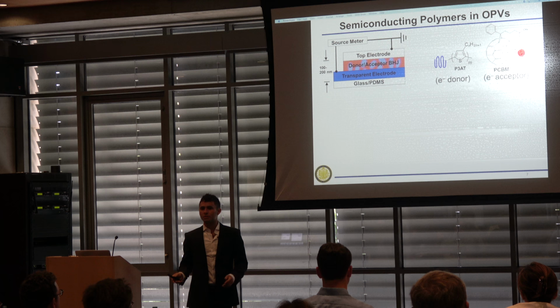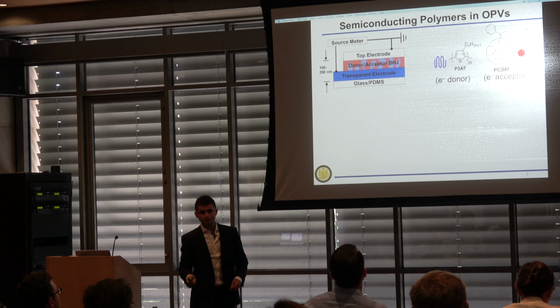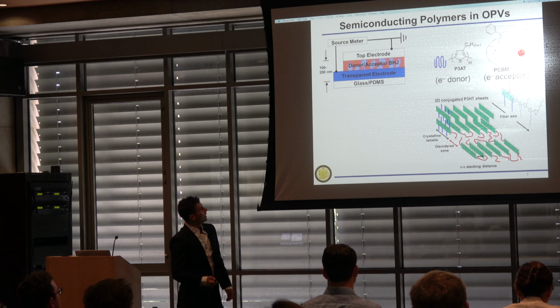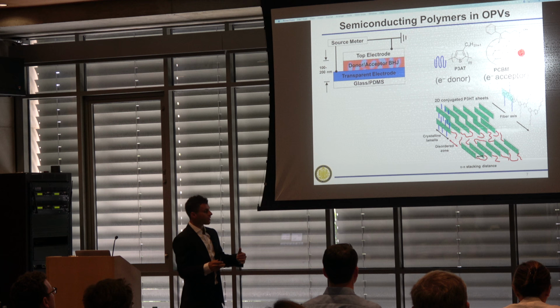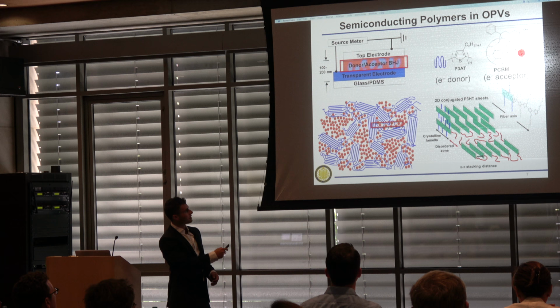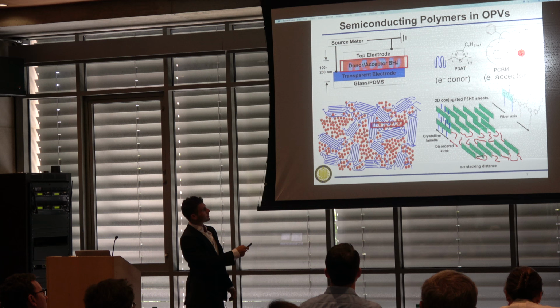The workhorse material of the field is a composite of poly-3-alkylthiophene, a conjugated polymer, and PCBM, a phenyl-C61-butyric acid methyl ester. And inside the bulk heterojunction, these two materials mix and rearrange themselves and phase separate in a bit of a complicated microstructure. We'll see here there's three phases, so it's a ternary phase structure. The first, there's two crystalline phases and a very disordered phase.